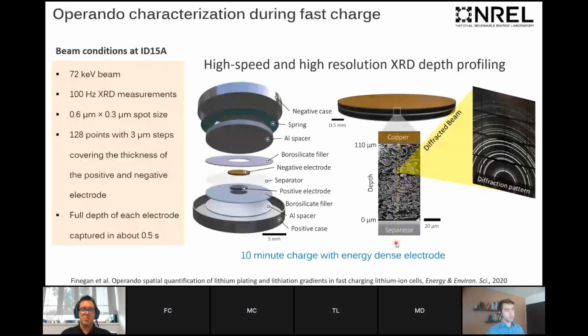And in this talk, I'm not going to cover the NMC electrode, but I'm just going to cover the graphite. And for the graphite electrode, with the speed of measurement at 100 XRD measurements per second, we captured the full depth of the graphite electrode in about half a second. So with about 3 micrometer resolution, we were able to see the composition of graphite, the lithiation state of graphite, with a resolution of 3 micrometers, captured in about half a second. So very good spatial and temporal resolution.